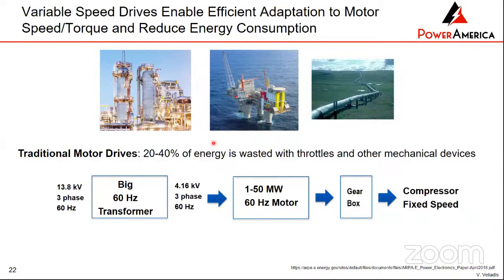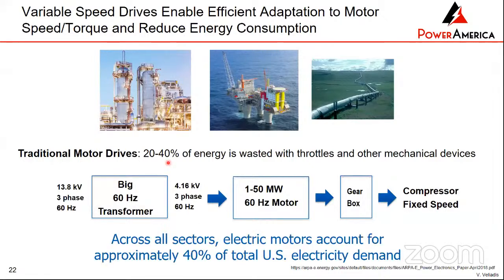Okay, when it comes to electric motors, you see these big installations here. They're using very massive motors. And if you make motors in the traditional way where the frequency is fixed, you're wasting about 20 to 40% of the energy. And I will point out that across all the sectors, electric motors account for about 40% of total electricity used in the United States, and about 60% of the electricity used in Europe. So it's a very high use for electricity in motors.